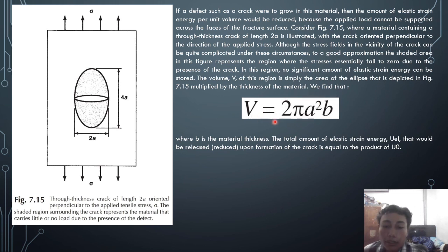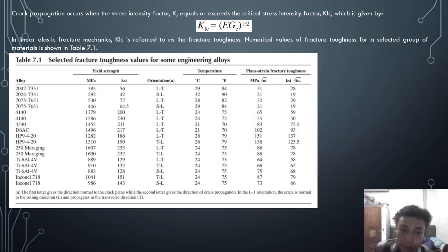We find that V is 2πa²B, where B is the material thickness. The total elastic strain energy U will be the energy released upon fracture as the crack propagates. Of course, the crack propagates when the stress intensity factor K exceeds the critical stress intensity factor KIC, which is given by KIC = √(EGC), Equation 7.12. KIC is the plane strain fracture toughness. A material with a higher value has greater toughness, as shown for a selection of materials in Table 7.1. This is Table 7.1.